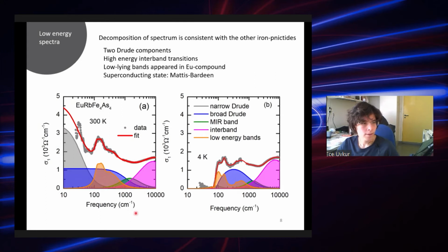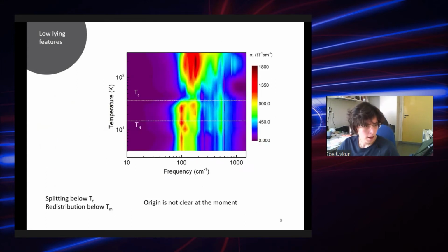When we move to the superconducting state, everything pretty much stays the same, except the Drude component, which contributes to the superconducting gap, so you can describe it with a Mattis-Bardeen approximation, where this low energy part of the Drude component just disappears. As I said, these low-lying features were kind of weird and different from the calcium-potassium case. So here I plotted the intensity of these as a function of temperature and frequency. The origin is not clear at the moment, but they respond to the superconducting state. When we go into the superconducting state, they kind of split.